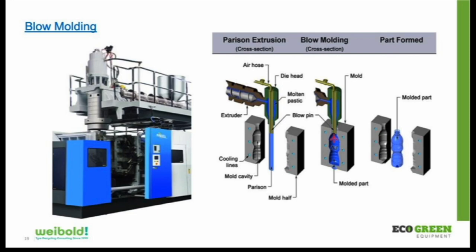And what that means is these are on timers. So when we say, okay, time to extrude the parison, we want it to always be, say, 15 seconds to extrude that whole thing. If we do it in 15 seconds with one material, it's right at the bottom of the mold. When the mold closes, we don't have much of a tail, which is scrap that has to be reground. Whereas if it comes out very fast because melt flow is off, now you have a long tail and you have a lot of material.